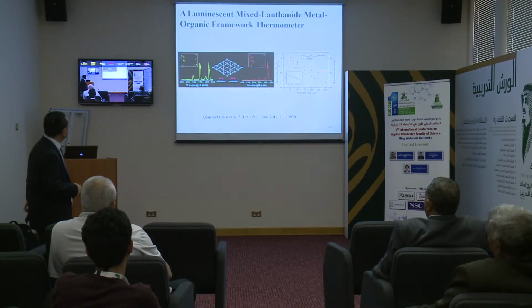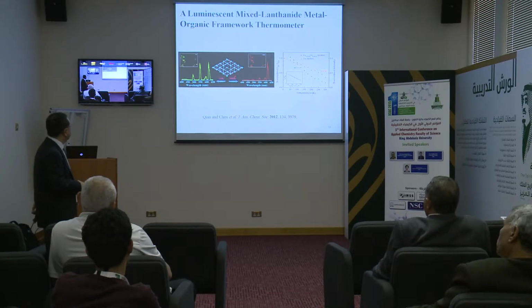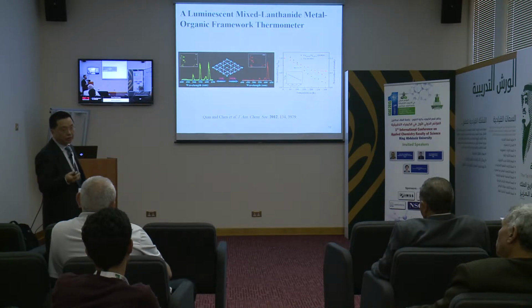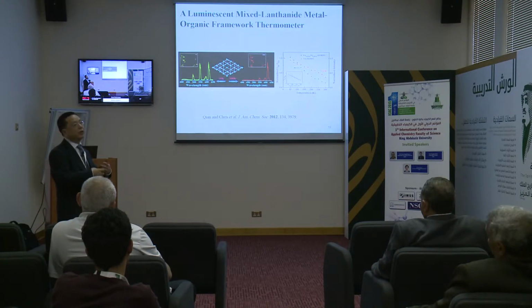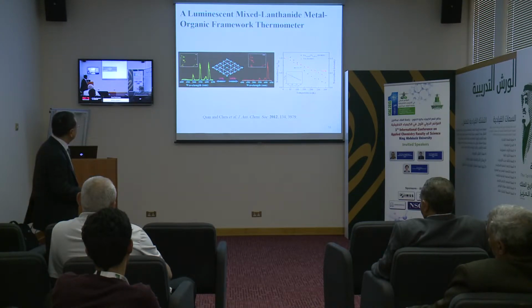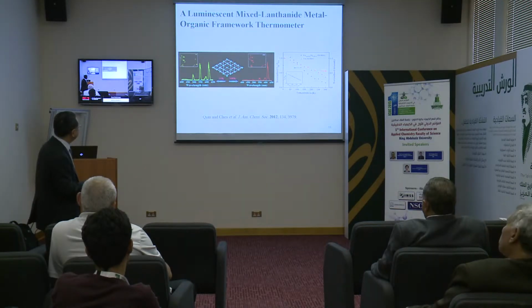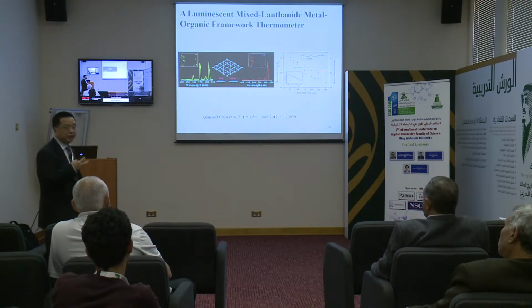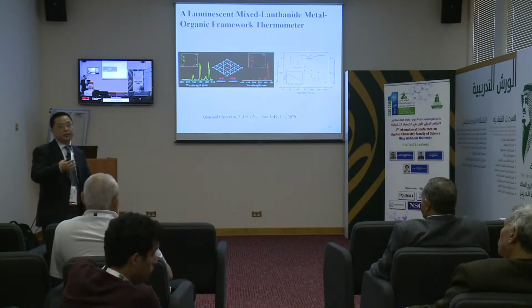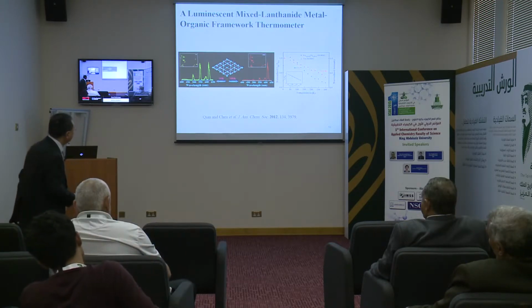And this is another one. This basically is not a porous material. It's a coordination polymer, but we know that with lanthanide metal organic framework coordination polymers, we can easily synthesize isostructures. We can use doping. So we dope one component, terbium or europium, into the terbium MOF materials, and then we have 2 luminescence centers, and they are temperature dependent. Based on that, we can establish a linear relationship with the temperature. So here, basically 2 luminescence centers, without any calibrations, robust and reliable.